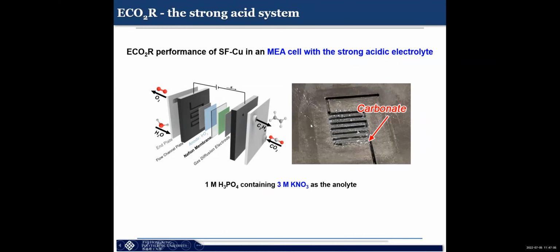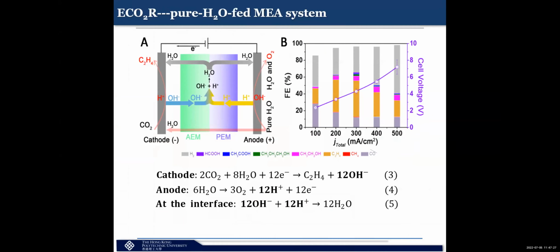But if we do not use very strong acid, the carbonate formation will actually block the pores, and then cause flooding and all this. So it will reduce the stability. So for us, we thought of a way: in the introduction, people mentioned that if you use pure water to flood into the cell, you can actually reduce or prolong the formation of this carbonate. So for us, we only use pure water. So this is the thinking: no alkalis, no acid, just pure water.